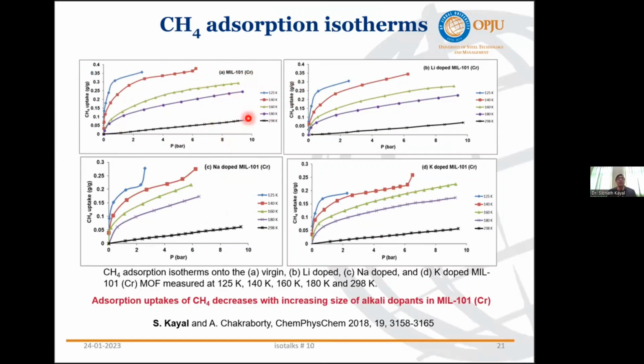Let's say MIL-101 chromium. You can see the adsorption characteristic decreases with increasing temperature. With pressure, as we increase the pressure, the adsorption capacity also increases. And whenever we dope with lithium ion, what happens? The adsorption characteristic decreases. Similarly, when you dope with sodium, the adsorption capacity decreases further. And when you dope with potassium, the adsorption capacity is lowest.